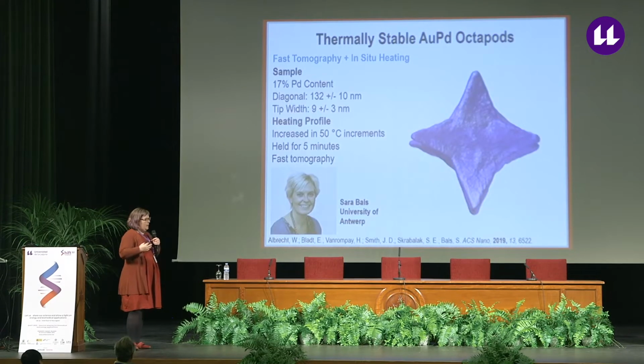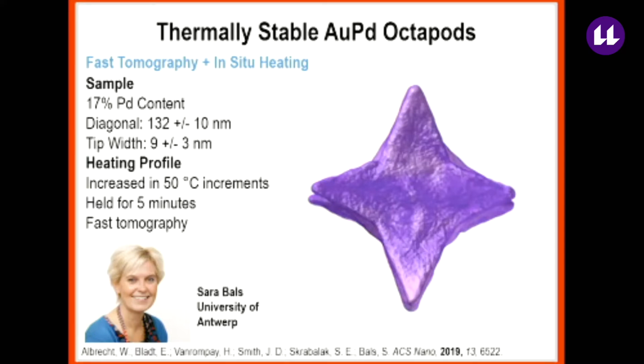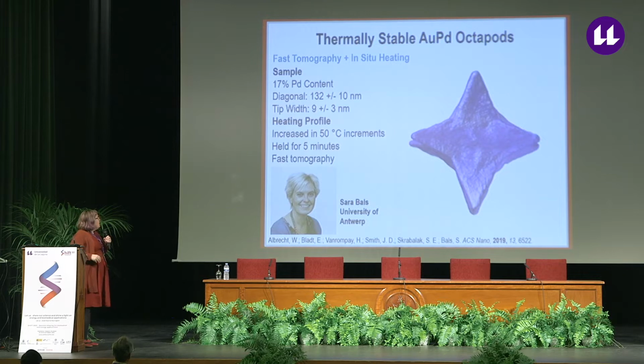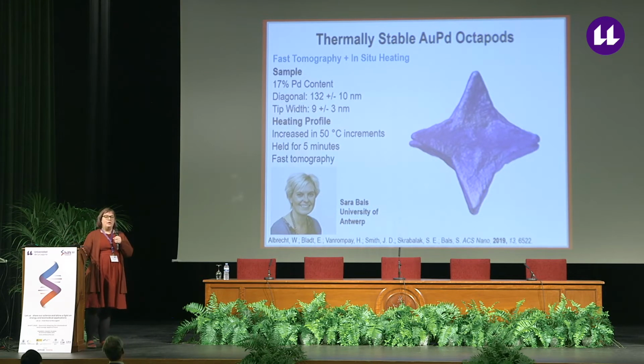And to try to get some quantitative information on just how stable these nanocrystals may be thermally, we turned to Sara Bals' group, who you've gotten to see a lot of her wonderful work this week. And one of the techniques that her group has been pioneering is that of fast tomography, where they can collect a tomographic series in 10-15 minutes. And this allows you to do more in situ style work. And so here they took our branched gold palladium nanocrystals and put them onto an in situ TEM holder where you could heat up your sample within the electron microscope. And they heated the nanocrystals in 50-degree increments and held it for 5 minutes, then applied their fast tomography.